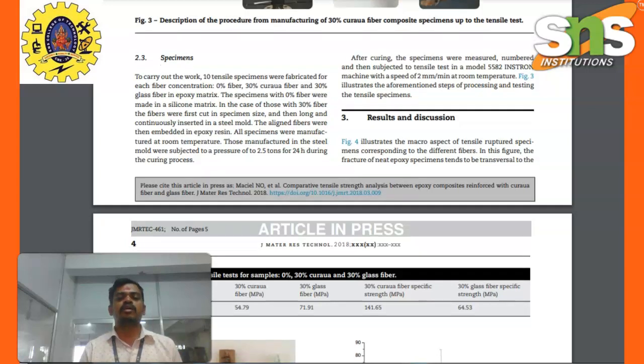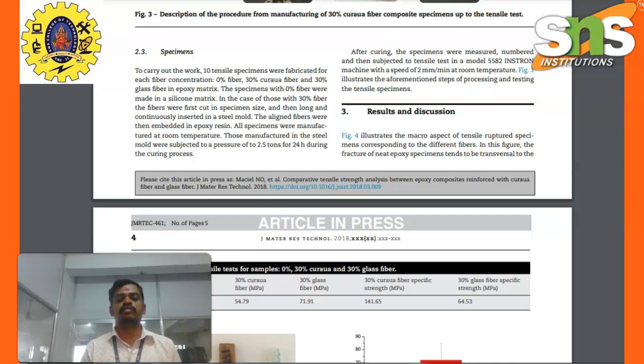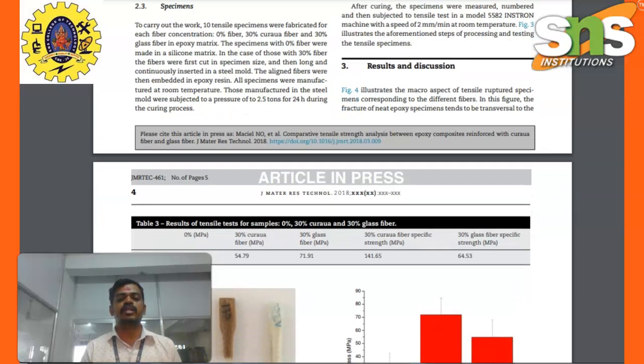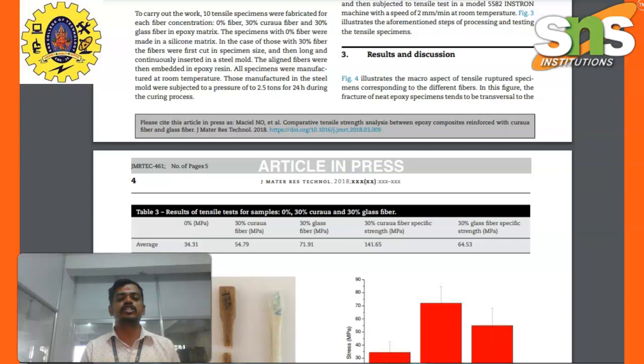To carry out the work, tensile test specimens were fabricated for each fiber concentration with 0% fiber, 30% curaua fibers, and 30% glass fiber in epoxy matrix. The specimen with 0% fiber was made in a silicone mold. In this case, those with 30% of fiber were cut to the specimen size, then long continuous fibers were inserted in the steel mold. Aligned, the fibers were then embedded in epoxy resin.